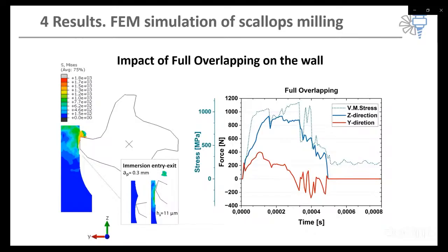We carried out detailed simulations to observe how overlapping scallop passes impact the part behavior depending on the overlapping fractions. This slide shows the result of full overlapping in the milling process. The tool fully overlaps the previous scallop pass, which leads to much more uniform contact with the surface. The actual residual scallop height in this case was reduced to 11 microns.